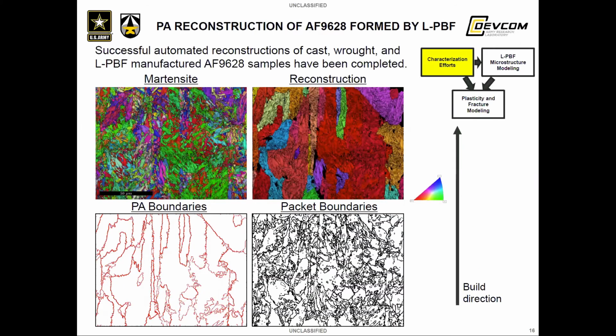Now for some additively manufactured samples. This slide depicts reconstruction results for AF9628 formed via laser powder bed fusion. The martensitic structure is depicted by EBSD in the top left image. The reconstructed austenite grains are shown in the top right, and immediately apparent is the typically vertical alignment of the austenite grains with respect to the build direction, which is defined by the arrow on the right. The austenite grains are clearly undergoing the same type of epitaxial growth that's shown by other materials formed by laser powder bed fusion.